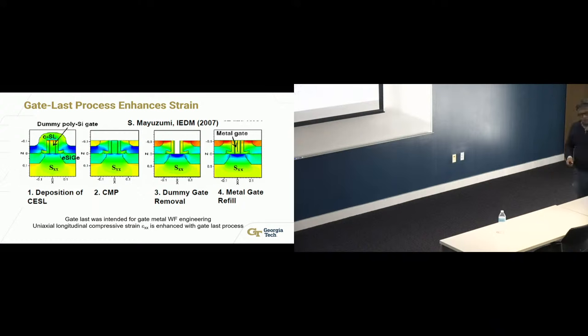We realized that in order to actually make this metal gate and high K process work, with the right work function of the two metal gates to target the threshold voltage of NMOS and PMOS, we could not do that with the conventional transistor processing. What was the conventional processing? Conventional processing means you define the gate for both N and P, and then you do a self-aligned spacer, and a self-aligned implant and activation of the source and drain regions. That high temperature process is a big problem for these metal gates. Not necessarily that they will melt or anything, but it will shift the work function because of very complicated interface dipoles that show up when you go through those high temperature steps.